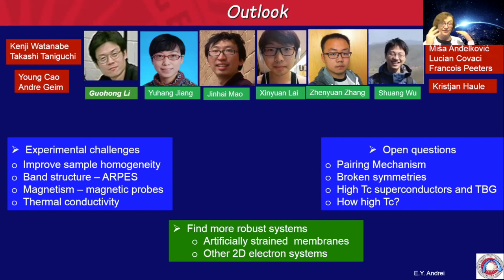We'd like to actually get direct access to the band structure by doing angle-resolved photoemission. We'd like to have magnetic probes to probe the magnetism of these layers when they're partially filled, and measure thermal conductivity to get some idea about the coupling in the superconducting phase. Many theoretical open questions: what is the pairing mechanism? What are the broken symmetries that give rise to these new phases? Can our understanding of this system shed some light on the high temperature superconductors, and how high can we push the Tc of superconductivity? Can we get to room temperature superconductivity?